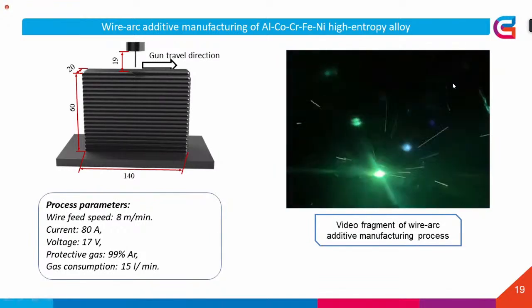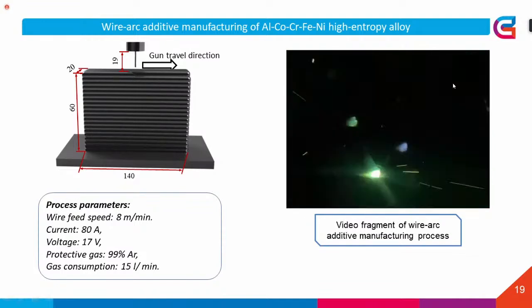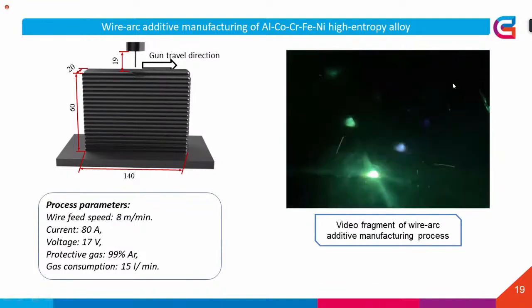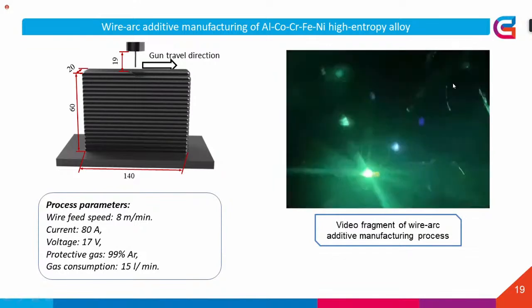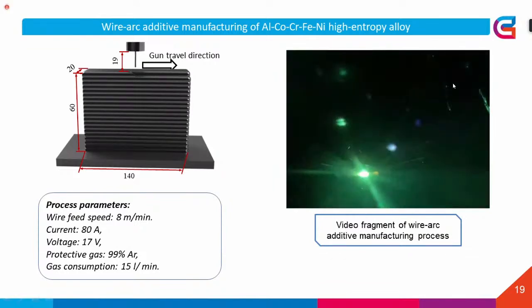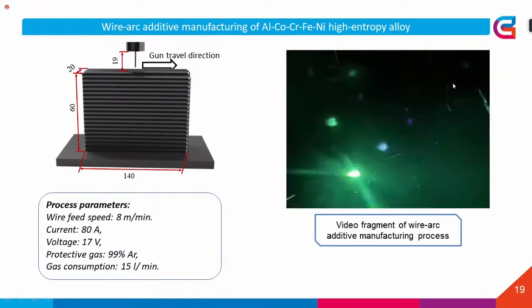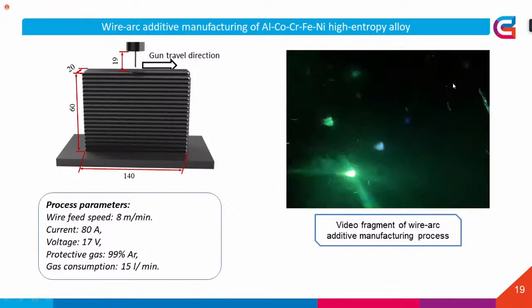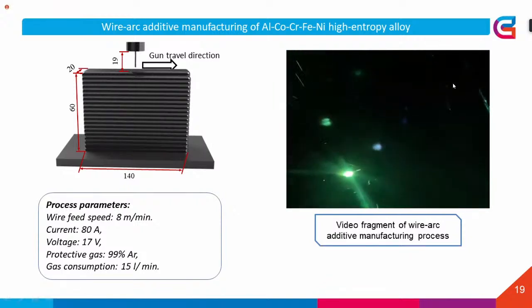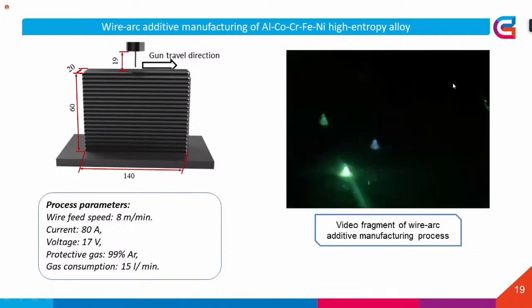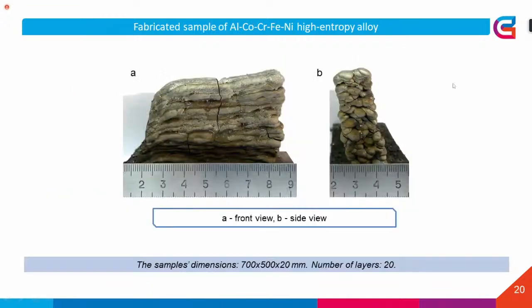So you can see the video fragment of the manufacturing process of the wire arc additive. Different parameters of the process are shown: the wire feed speed, the current, the speed of gas consumption. About 20 layers have been applied, and you can see the sizes. For the experimental pattern, it was enough at this stage. This is one of the fabricated samples.